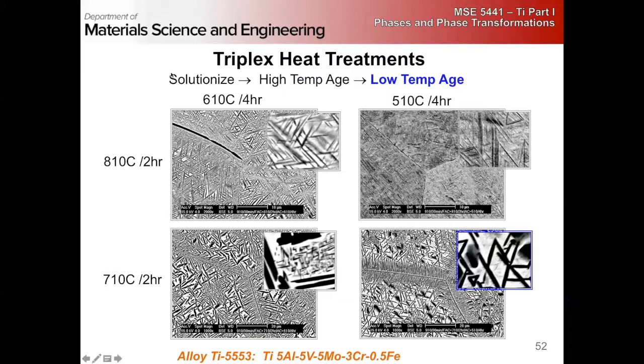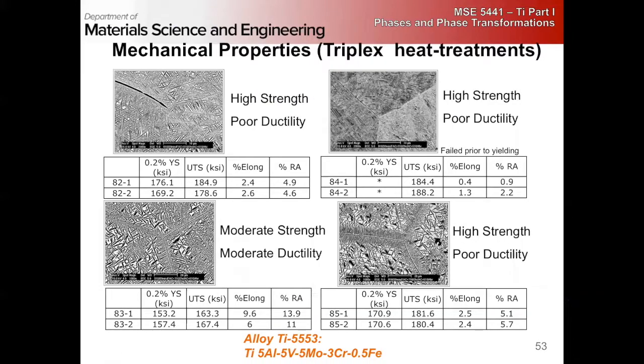But basically, the idea behind these triplex heat treatments is going to be a solutionize, then an oil quench, and then a high temperature, and then a low temperature aging. And depending on how you play with this, you could get different structures, and you'll notice that they don't have recipes up here.